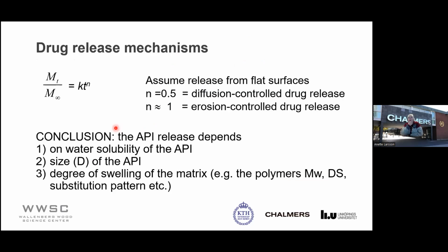And what people very often do is that they determine the fraction released as a function of the time raised to an exponential factor here. And if you have flat surfaces, the exponent factor should be 0.5 if it is completely diffusion controlled, and approximately equal to 1 if it is erosion controlled. So very often you can see in release studies that they have determined this factor here.